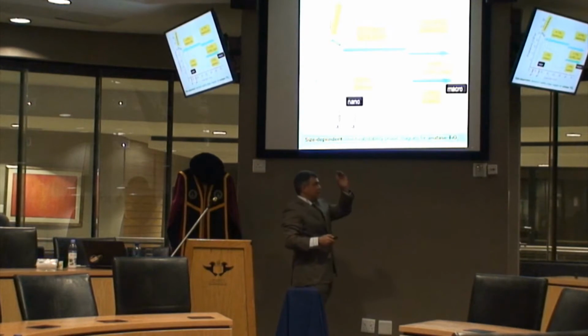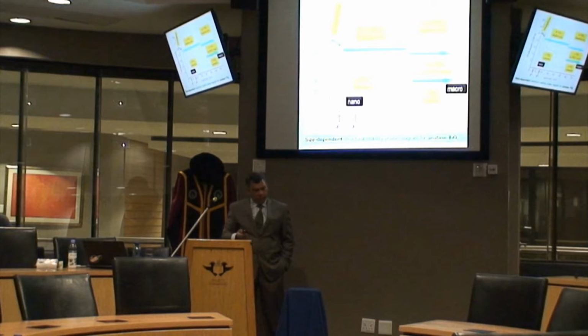And we then, out of all of that, were able to develop this phase diagram, if I may call it that. I've plotted pressure here as a function of the size of the grains. And when we're dealing with the bulk, macro-sized grains, I haven't shown this to you. It actually starts off in this T phase, converts to a phase two, and then converts to a third structural phase. Okay? And yet I showed you in the nanophase, it remains in this T phase. It's ultra stable, and eventually it goes amorphous, disordered. And we're interested in that disordered phase.